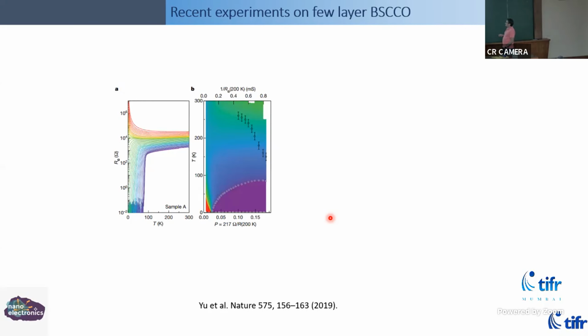Even more, a relatively recent, cool experiment out of Fudan University in China used the same crystal, but they exposed it to ozone, which is essentially tuning the oxygen stoichiometry. By tuning the ozone exposure, they can tune through the whole phase diagram in the same device, which is analogous to making a transistor-like geometry.